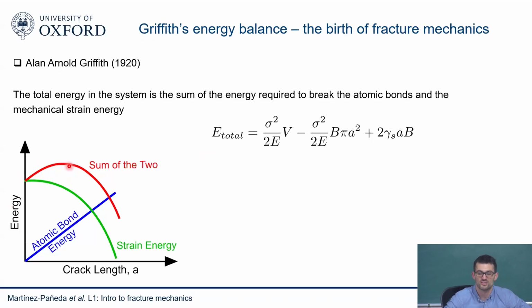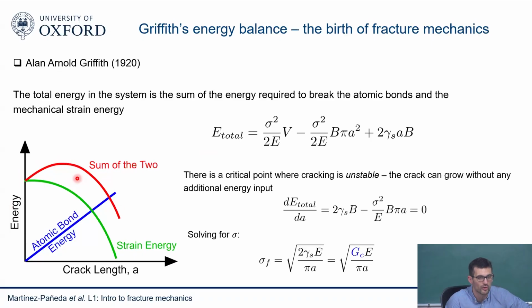Cracking is going to appear in an unstable way. My crack is going to grow immediately without the need for any more applied energy. So there's a critical point where cracking is unstable. The crack can grow without any additional energy input. So this is a maximum. If we want to get maximums or minimums, as you know, we take derivatives and equate to 0.